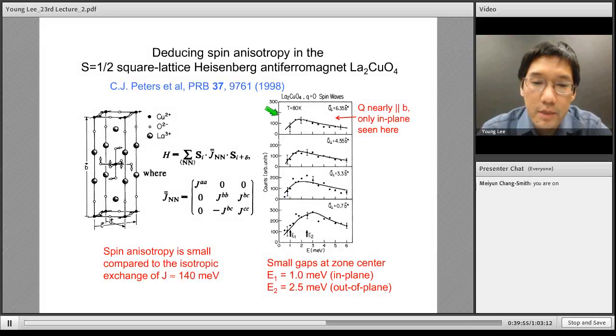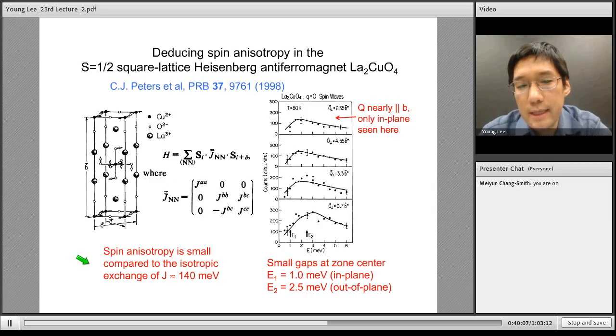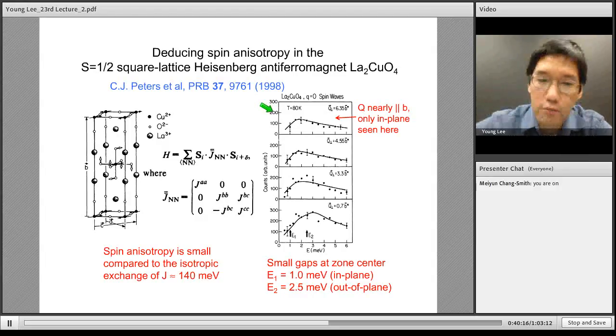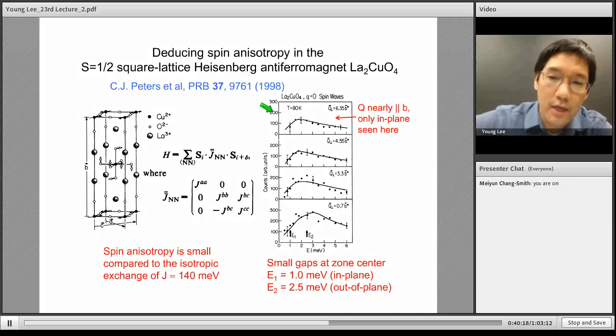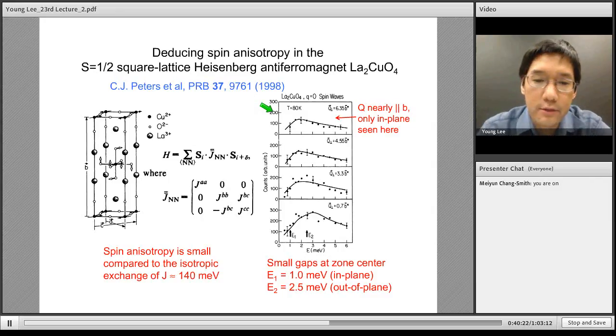So on the top here, they're claiming that only the in-plane mode is seen, and you can deduce some energy gap of about 1 meV. And here, you're not seeing a sharp peak, but you don't expect to. Again, the exchange is really large. It's 140 meV. So you're going to just see more of a threshold for scattering, and then a lot of weight to higher energies. So it's this threshold that I guess that they're fitting.